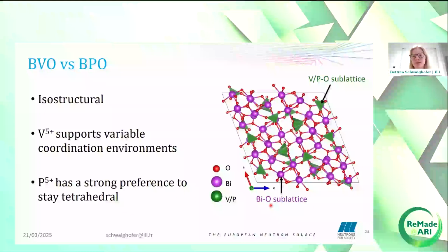These two materials are isostructural, so they adopt the same monoclinic ordered fluorite superstructure, which you can see here, consisting of two sublattices each, a bismuth oxygen sublattice and a dopant sublattice. The main difference between them is that vanadium readily supports variable coordination environments, whereas phosphorus has a strong preference to stay tetrahedral. We also know from impedance measurements that the vanadate has a significantly higher ionic conductivity by almost an order of magnitude than the phosphate. Therefore, these two materials are a great opportunity to study the effect of the dopant on the localized and long-range diffusion.